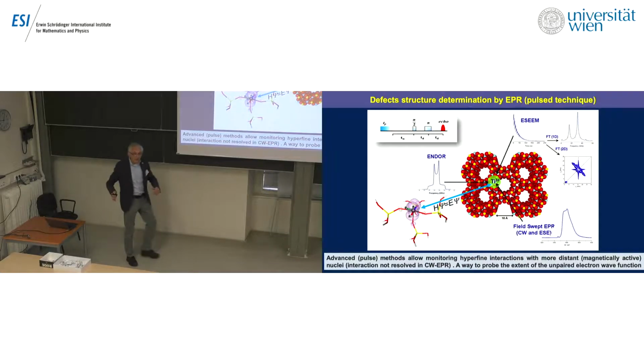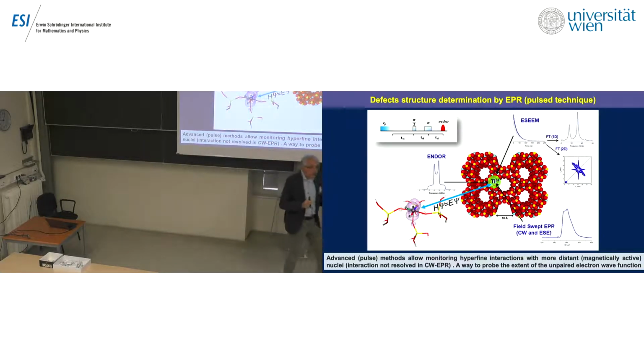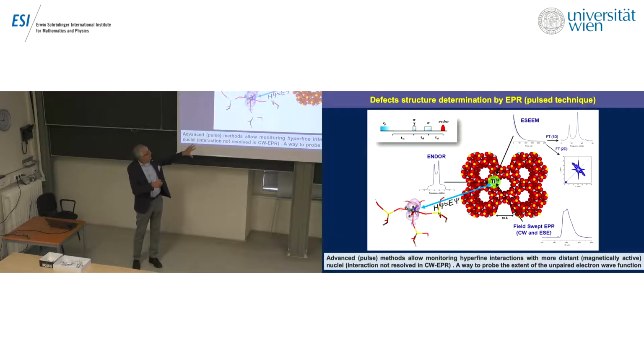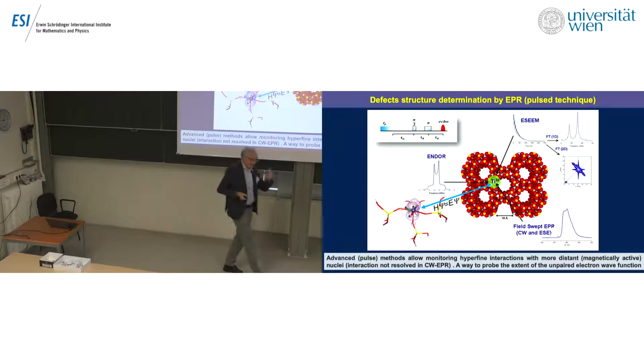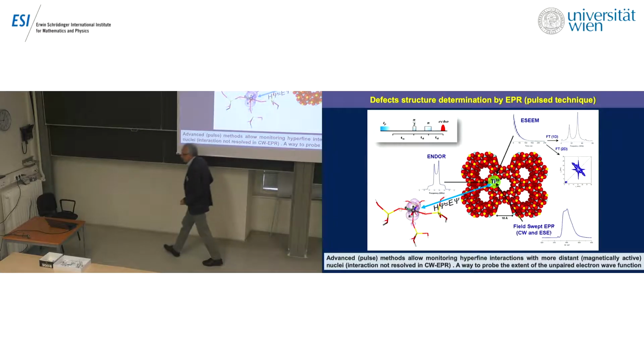There are two kinds of approach in EPR. The classic one is the so-called CW, continuous wave EPR. You have simply a magnetic field that sweeps a certain region of magnetic field, and the sample is irradiated by a microwave. When resonance occurs, you record a spectrum. Modern techniques are, on the contrary, based on pulsed EPR. There is a sequence of pulses. I cannot enter into the technicalities because there are many types of application. The main message we can keep in mind is that in this way you explore a wider region of your sample around the paramagnetic center, because you become able to detect much weaker interactions, in particular much weaker hyperfine couplings.